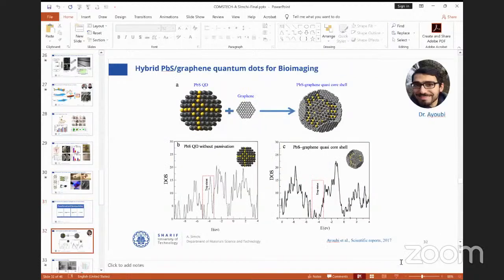The first work is for imaging purposes. Many nanoparticles have been used, but mostly they are not in the right wavelengths. We would like to have wavelengths around 800 to 900 nanometers, so we can image the nanoparticle or the carrier deep in the tissues. Most of them are in the green side or in the blue light. It's not useful. It can only be used on the surface. So one of the best candidates is lead sulfide.